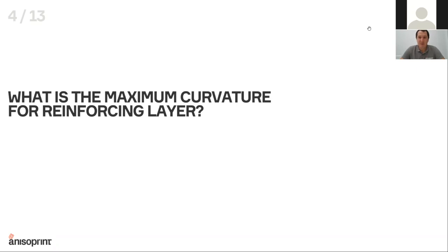But if you need to reinforce something like a hole, the minimum diameter of a reinforced entity, like a hole, will be about 8 millimeter. Because on a smaller radius, the absolute tolerance will be quite low. It's very hard to reinforce smaller features with good tolerance.